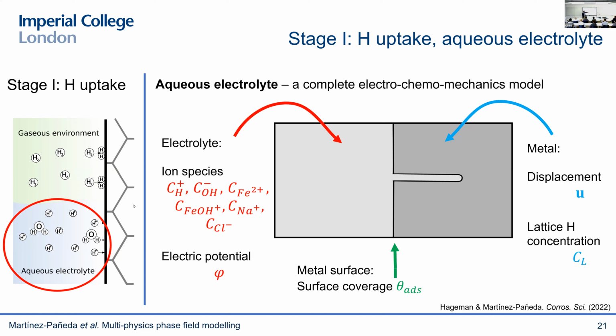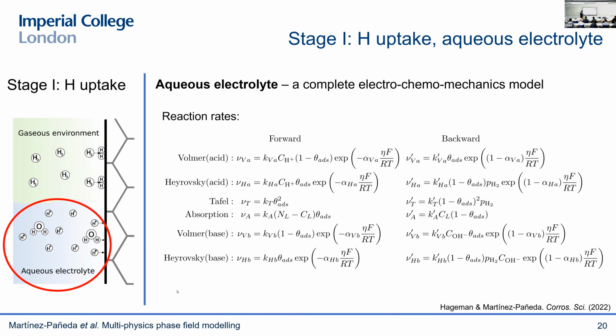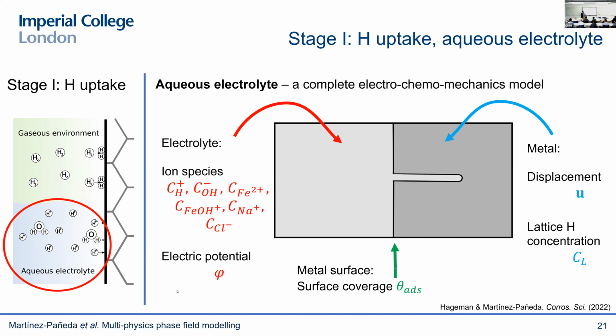So you have an electrolyte domain where you're solving for as many ionic species as needed. Then you're also solving for the electric potential. And then in the interface, you're solving for the hydrogen surface coverage. And then you have a metal, which may contain a crack, which you're solving for at the very least for the displacement and the hydrogen lattice concentration.